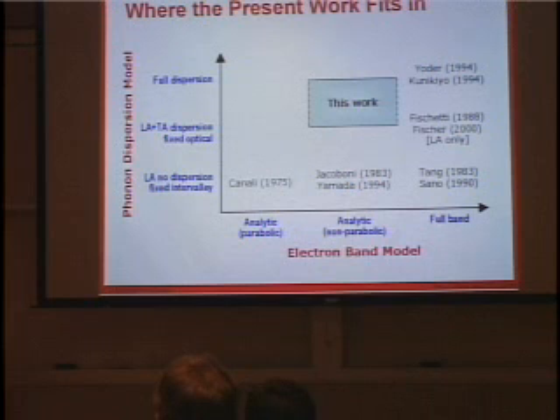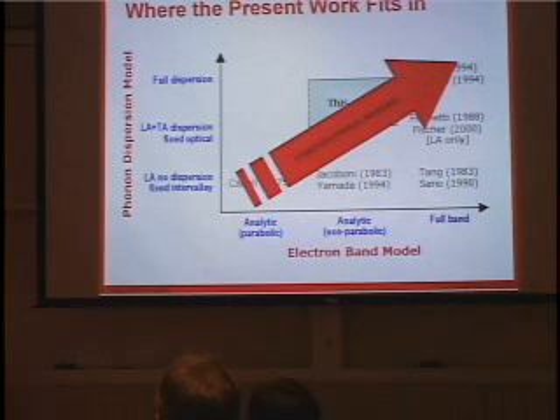About 10 years ago, some very daring scientists worked out a code that is extremely slow, but it actually uses the full phonon dispersion, computed from ab initio, essentially from basic principles, just like the electron band model. The problem with these kinds of approaches is that they get very, very computationally expensive, especially for the full band and the full dispersion approach.